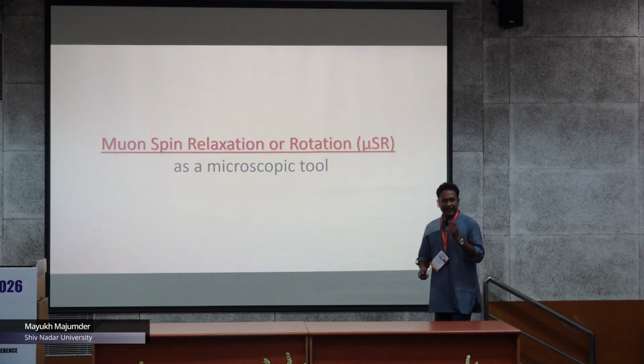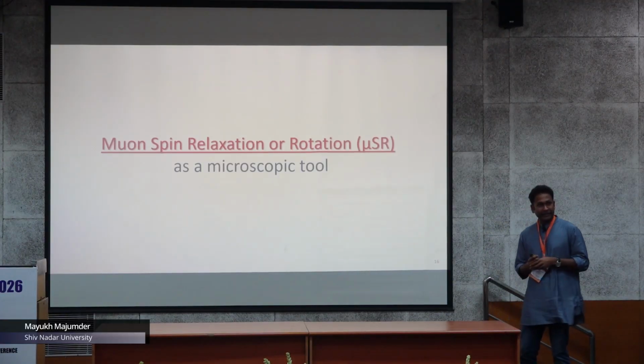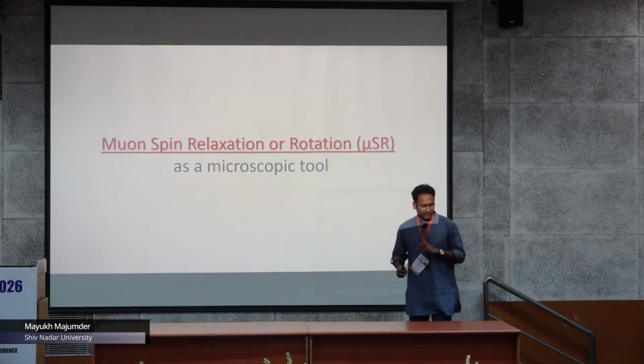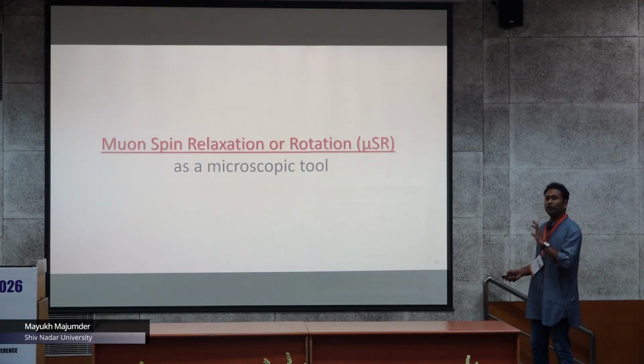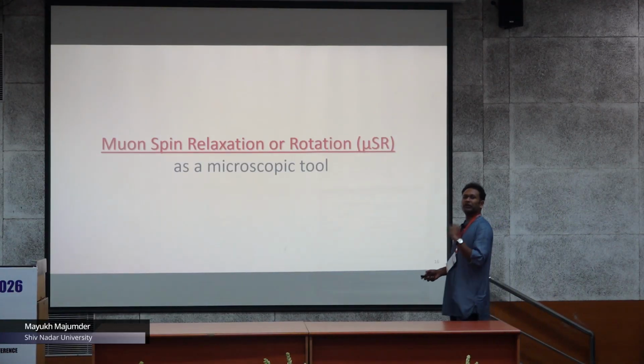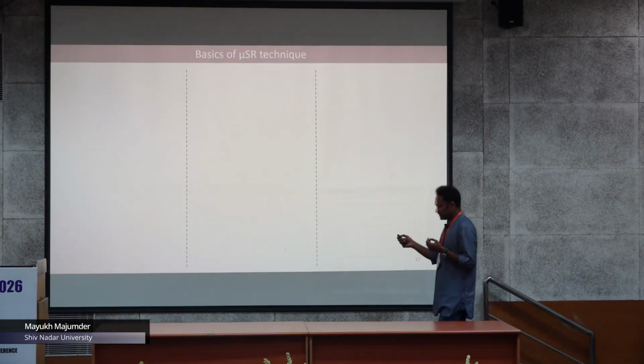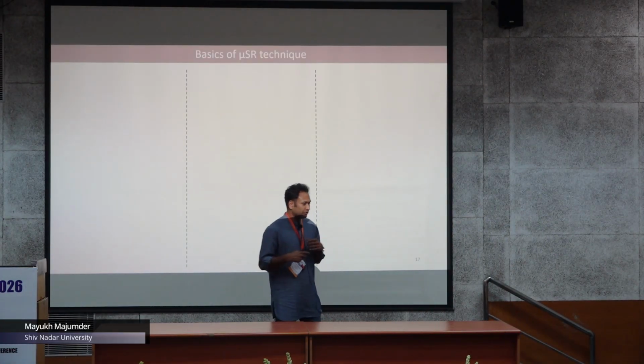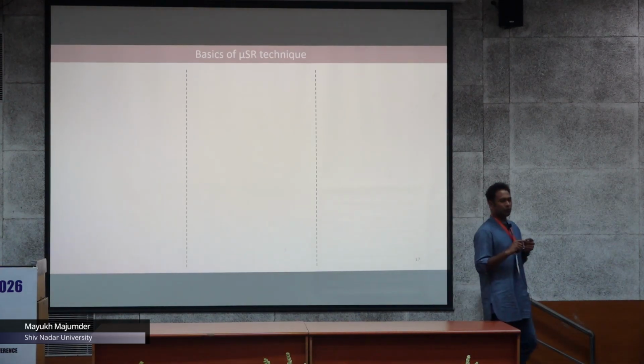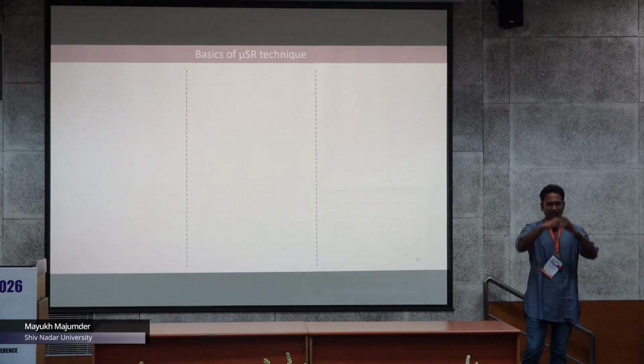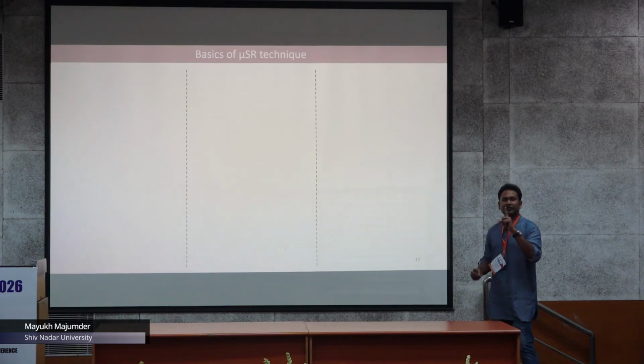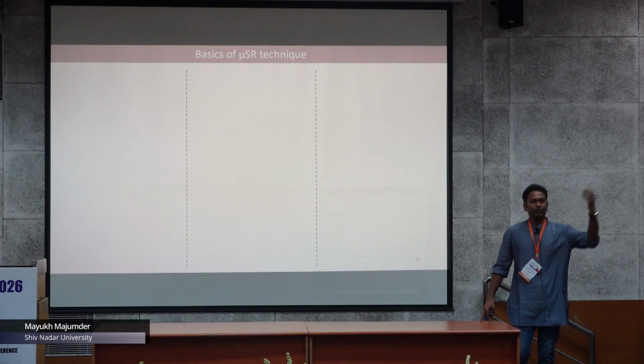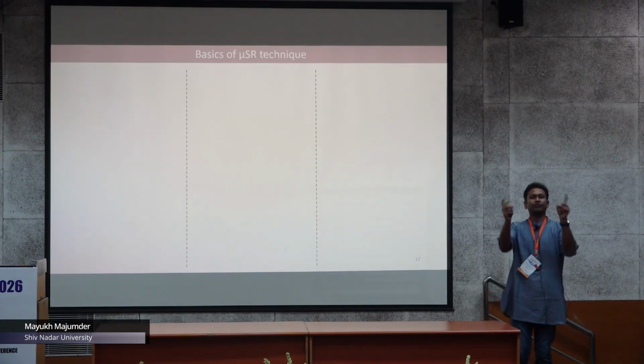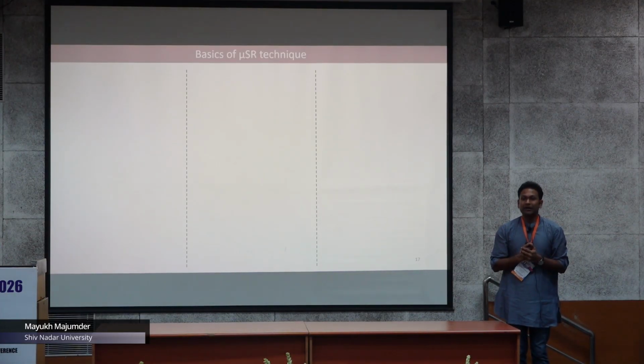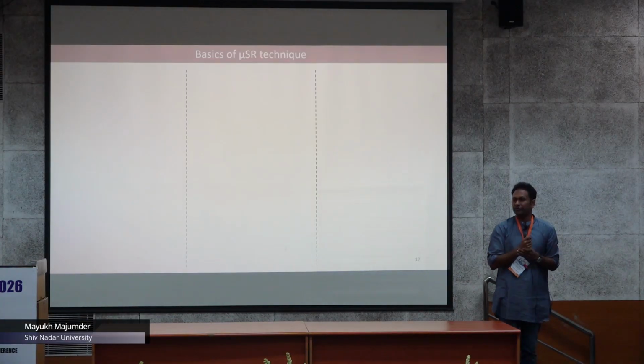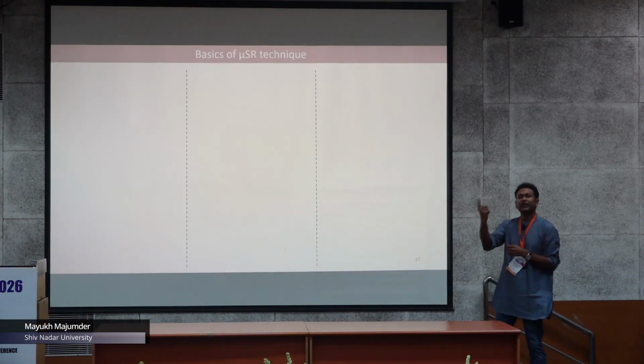So in order to verify that, we have employed the muon spin relaxation or rotation technique as a microscopic tool. Of course, for the sake of time, I'm not going to talk about the technical details, but quickly go to the outcome, what sort of information one can get. So the basics of muSR is that the name itself suggests you are dealing with muons. If you implant the muons in some interstitial position of the crystal structure, the muon has a finite spin half, and if the system is at lower temperature, below an ordering temperature, then definitely the muon is going to experience some local field. And if it is experiencing some local field, it is definitely going to precess.